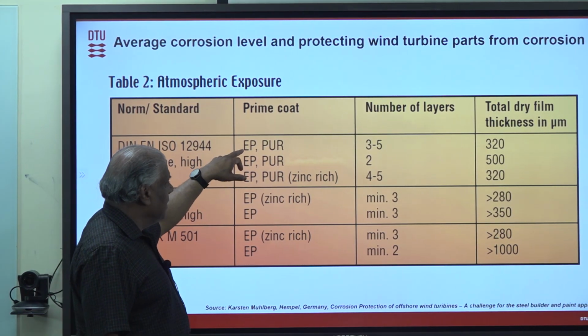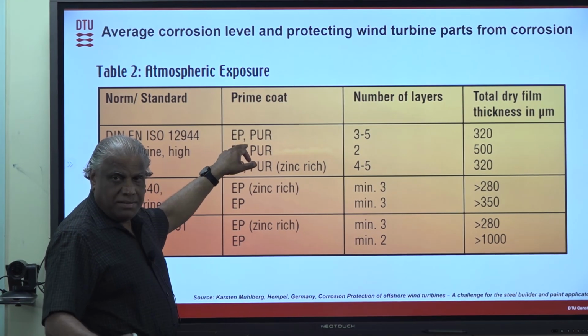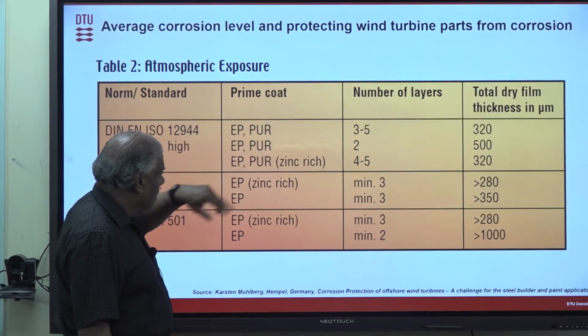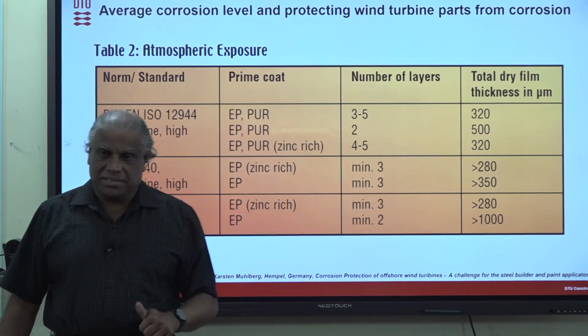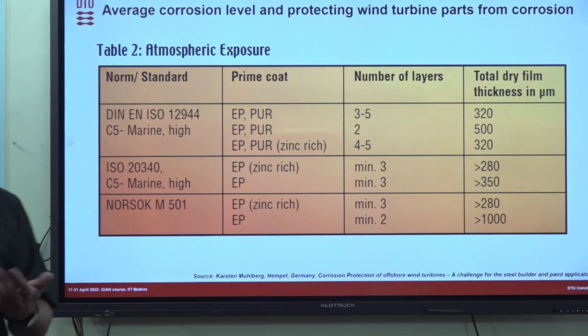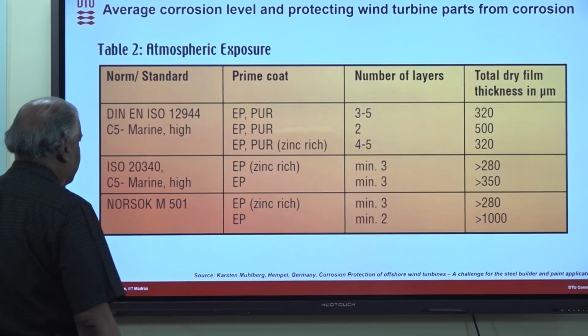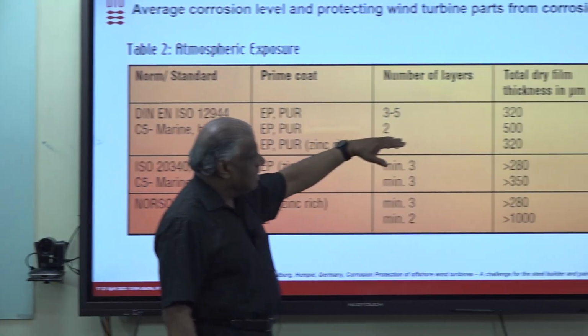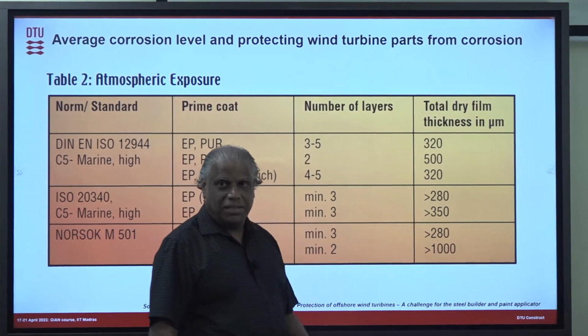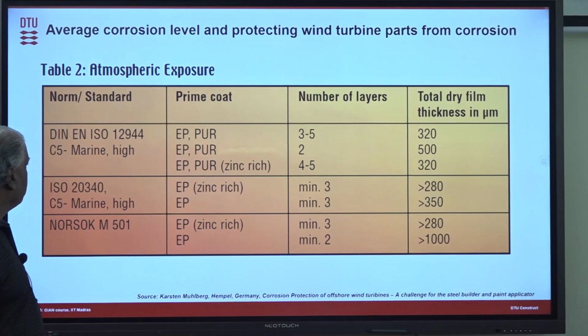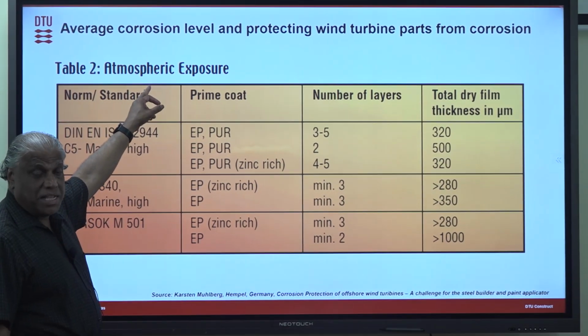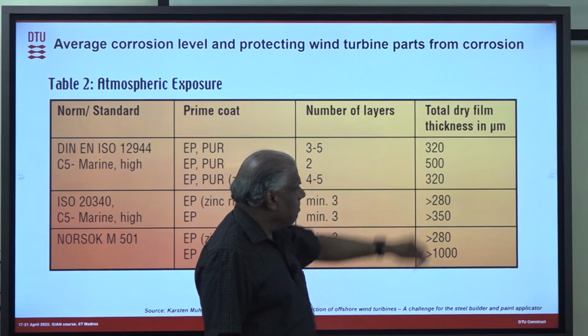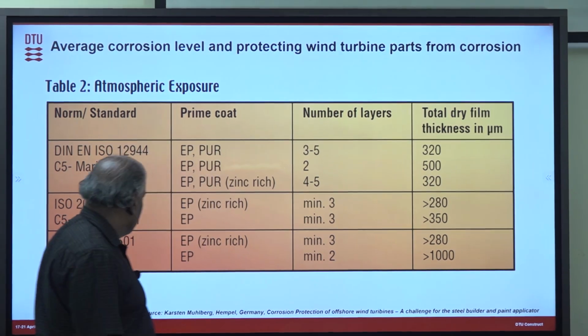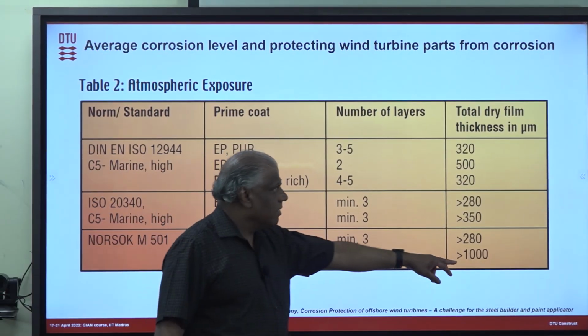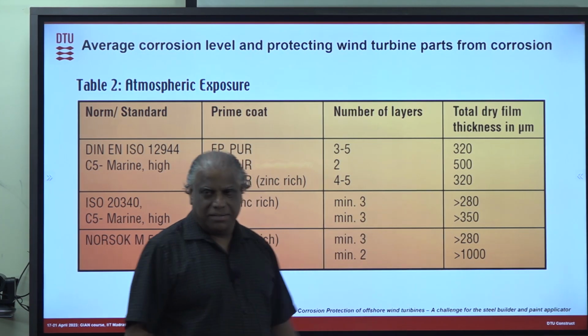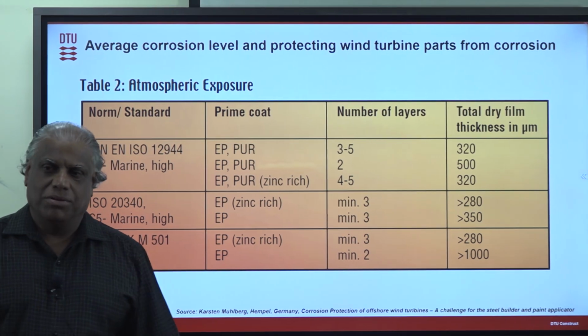So whenever you see EP, it means epoxy resin covered, and polyurethane is PUR, and PUR zinc rich means the PUR also contains zinc plates, so that it will act as a galvanic, like a zinc coating, and that's why it is zinc rich. And you can see that they put many layers, almost a thickness of around 320 micrometer. This is the atmospheric exposure part. Here they put around 320 micrometer thickness, and actually the NORSOK is much higher than that. It goes up to around 1000 microns. So it's quite a big thickness of paint which they put all together to protect it from corrosion.